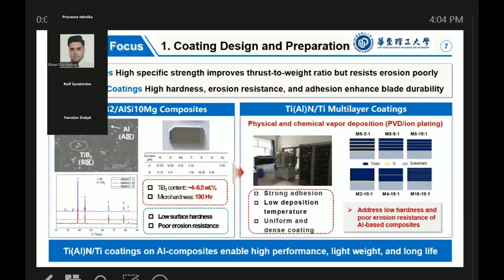The first part concerns coating design and preparation. We started with aluminum matrix composites, known for their high specific strength, which improve the thrust-to-weight ratio of engines. To enhance erosion resistance, multi-layer coatings that balance hardness and toughness were designed. In this work, titanium aluminum nitride on titanium coatings were deposited using multi-arc ion plating, meeting requirements for lightweight design